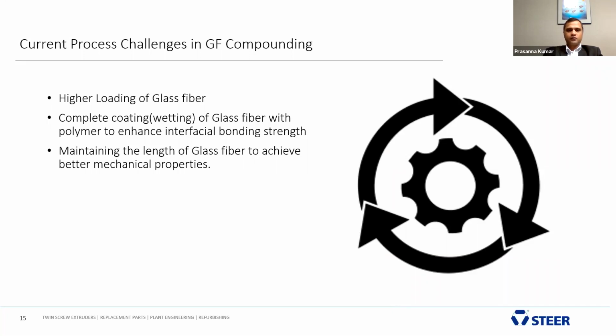So the challenges that we have foreseen, and from our feedback from our customers as well, is that higher loading of glass fiber is not possible with the existing processing zone. Complete coating or wetting of glass fiber with polymer to enhance interfacial bonding strength, and maintaining the length of the glass fiber to achieve better mechanical properties. These are some of the process challenges while compounding nylon with glass fiber.